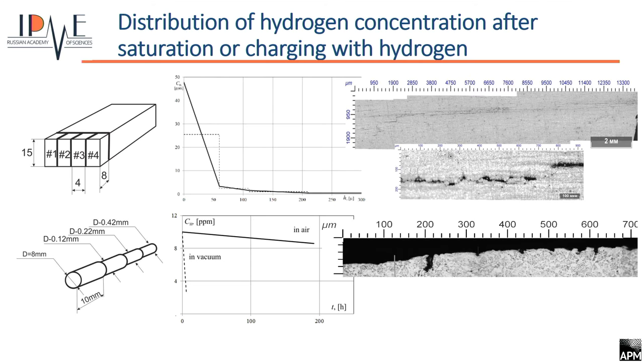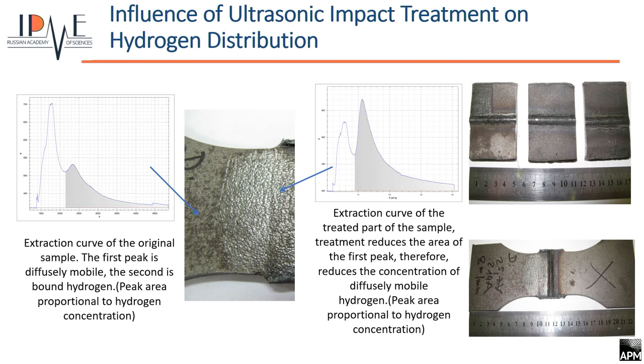The same results during the interaction of metals with an aggressive environment, aggressive with hydrogen or with electrolyte, and here we also determine some skin effect. We damage only a very thin layer of the sample, but the sample really decreases its mechanical properties, and this maybe in two times. Here you can see also a very interesting experiment.